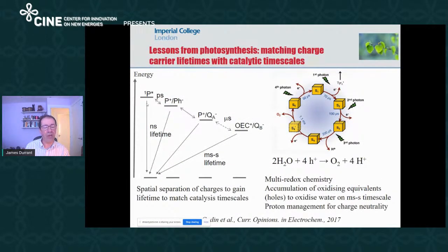In terms of how it works, there's particularly a lifetime challenge, which I find interesting. When you absorb a photon by chlorophyll, the lifetime is nanoseconds. If you want to drive catalysis, for example, the catalysis of water oxidation, then the lifetime is milliseconds to seconds of those catalytic centers. And so you have a challenge. You have excited states living for nanoseconds, and you want to drive chemistry on the millisecond to second timescale.